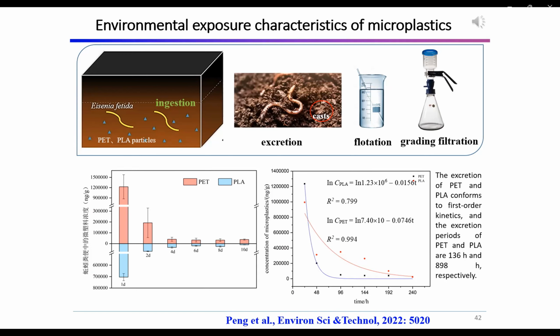Without considering the particle size distribution, excretion of PET and PLA in earthworms could be well described by first-order kinetics, according to the total mass of polymers in the earthworm casts. The elimination rate constant for PET and PLA in earthworms could be calculated, which indicated that PET microplastic was eliminated more quickly than PLA.